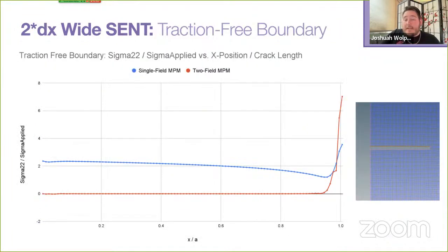More specifically, we can again look at the particle tractions of these 2 specimens, and here we again observe single-field MPM's difficulty with the discontinuity, but even better, we see that we now have a traction-free crack surface modeled by our two-field approach. So clearly, this two-field approach works much better given a little bit of enriched resolution at the crack surface. And now that we've seen that we can model a nearly sharp crack with two-field MPM, let's further see how well this captures a couple other fracture mechanics results for the SENT test.